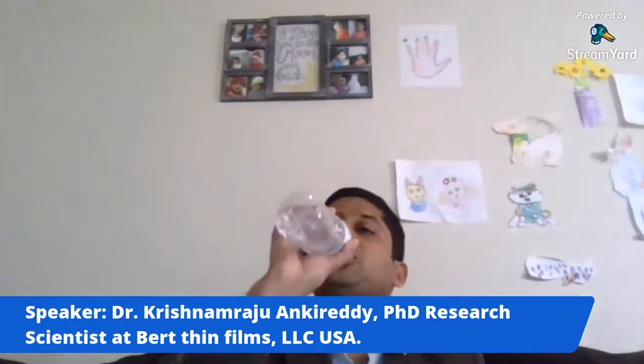I did this research long back, where I synthesized the nanoparticles. Earlier I talked about the two stabilization mechanisms: steric stabilization and electrostatic stabilization. Here we are utilizing steric stabilization, meaning capping the nanoparticles with some organic molecules for the stabilization. For that purpose, we used carboxylic acids. Those are one type of organic molecules